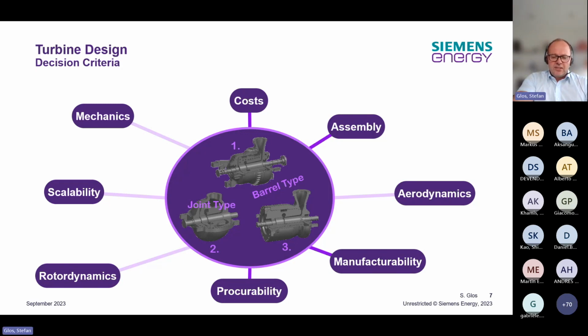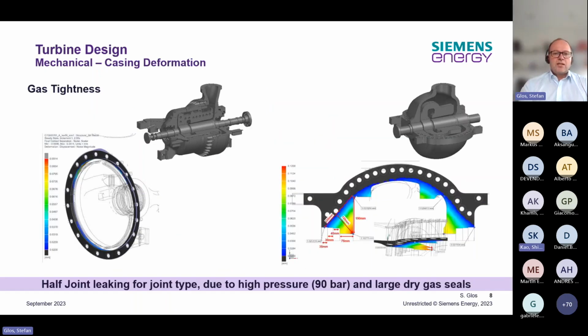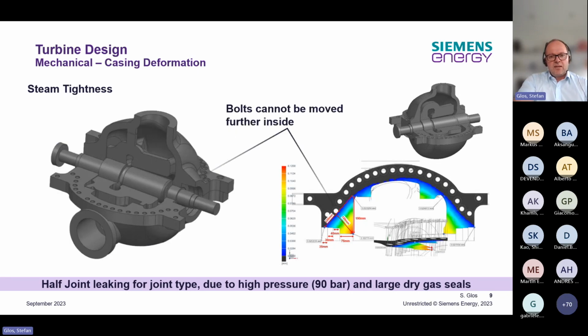And I will go a little bit into detail on one aspect which we checked, and which was a significant drawback for the joint type turbine on the right hand side, which was the gas tightness. Due to the high pressure and the fact that we had to implement the dry gas seal in the outer casing, the gas tightness was really hard to realize, whereas in the left concept, the barrel type machine, this was really no issue. Here you see it once again with another drawing, and this was really one of the largest drawbacks of this joint type turbine.